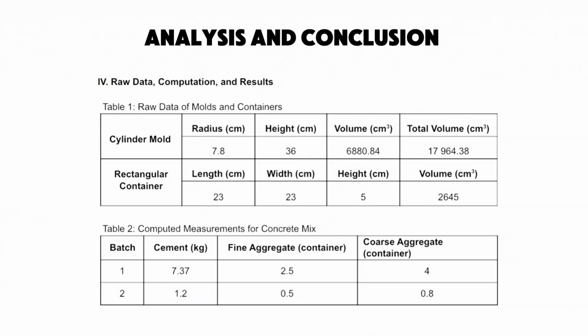standards. However, challenges arose during the mixing and molding process, particularly in achieving uniform consistency and eliminating air pockets. Uneven surfaces and visible air voids were observed, likely due to insufficient rodding and tapping, which could contribute to honeycombing and reduce durability of the concrete samples. The SLUMP test result of 3.8 inches in accordance with ASTM C143 confirmed that the concrete mix achieved an acceptable balance of workability and consistency, without excessive stiffness and fluidity.